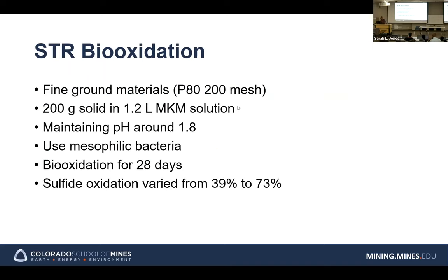So we ran some tests using 80% passing 200 mesh sample, pH control, and mesophile microorganisms in the biooxidation run for 28 days. I mean, usually in a fully developed plant, it takes only like 2 to 3 days. But in the lab scale, we use a little higher solid content, so it took a little longer, but it should be only 2 to 3 days. And the sulfide oxidation is anywhere between 40% and 70%.